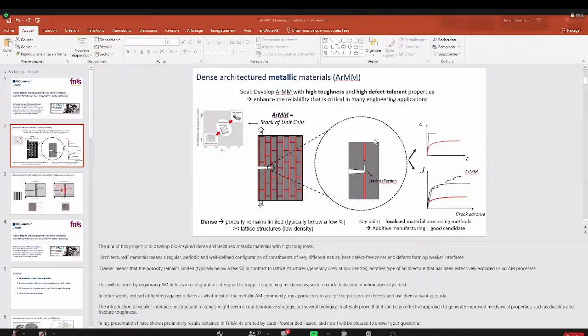Actually, after watching your presentation, it was quite interesting for me. We have also worked on a little bit easier cases, trying to redirect the crack path and eventually changing the fatigue failure mode from a mode 1 to a shear mode, so increasing the fatigue life. Of course, it was an architected structure. It was just defining some alternative path for the crack to propagate. And it was really nice and pleasing to see the results that you have obtained.